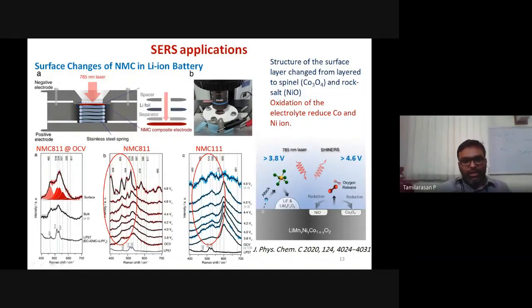Okay, and this peak is corresponding to the formation of cobalt oxide and nickel oxide. The cobalt oxide is a spinel structure, and the nickel oxide is a rock salt structure, and the formation is observed here for NMC 811 catalyst. But for NMC 111 catalyst, this formation is pretty much controlled here. So the relative intensity of this peak is not quite high compared to the NMC 811. So the conclusion is, compared to 811, the 111 catalyst is much better in terms of Co3O4 and NiO formation. Yes, the Co3O4 and NiO like oxide formation diminishes the performance of the catalyst.